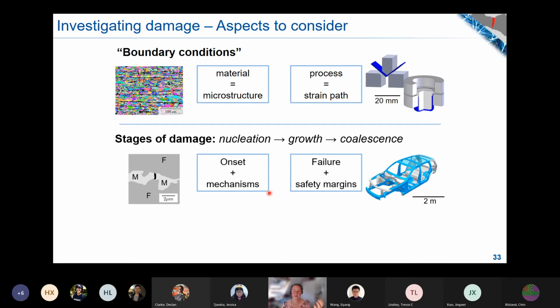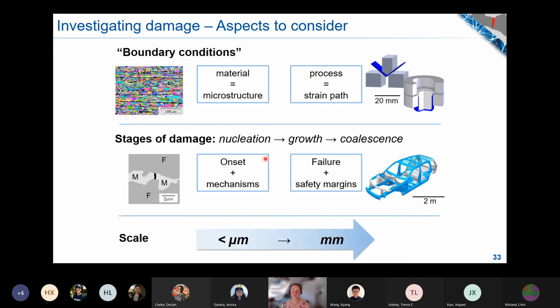And for us, we are interested in the underlying mechanisms. Where do I actually nucleate the first damage, and by which mechanisms do I do this? And then, of course, the important bit here is that I really have a scale bridging problem. Damage might nucleate at the nanoscale, but I need to cover the inhomogeneities that I have at least over the millimeter scale. That could be the thickness of a sheet, and that can also be the strain field or strain path that varies over a much larger area.